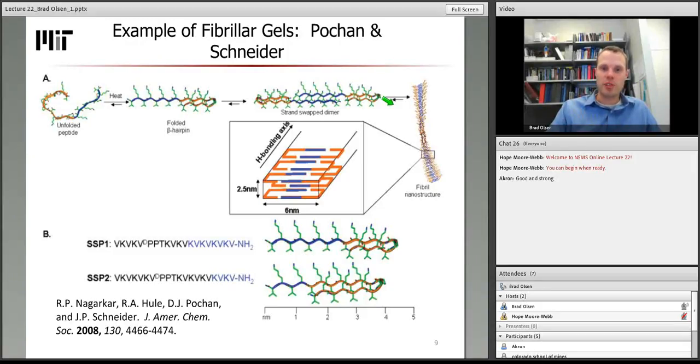Then these dimeric structures can assemble through hydrogen bonding between dimers into much, much larger fibers. So there are several length scales of self-assembly: the individual peptide folding, the peptide dimerizing, and then H bonding to self-assemble along a fiber axis to form an overall large length scale nanofiber structure, right? And so they show in this scale bar roughly the length of one of the folded peptides is of the order 4 nanometers, and as you'll see in some of the cryo-EM images, the length of the fibers can be much, much longer. This is very characteristic of these fibrillar structures.